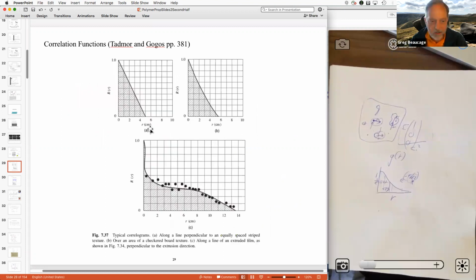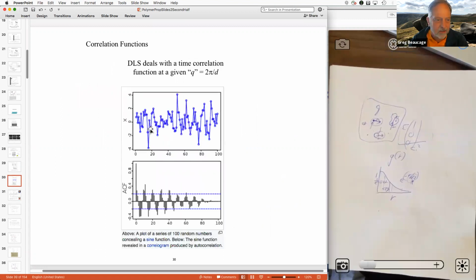this average length, right? So this just shows that this kind of correlation function analysis converts space to kind of inverse space. That would add a length. So you take space, which would be r, and it's converting it to q. Q is kind of an inverse space. So this process is basically the same thing as a Fourier transform.